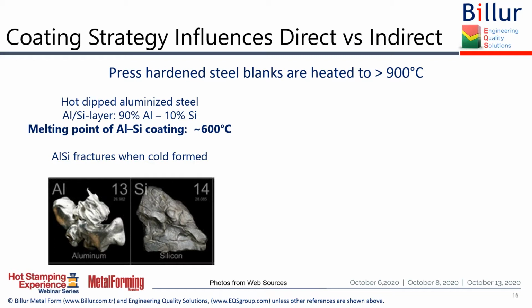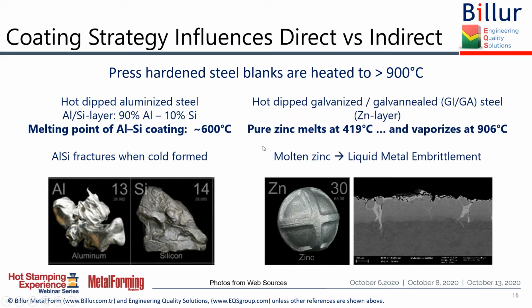The reason we select direct process with aluminum silicium coated is because if we cold form them, the coating breaks. And with the zinc coated ones, we have several problems. One is zinc melts around 420 degrees, and the second is it vaporizes around 906. So the austenitization temperature is about 885. I have to have a very narrow process window.